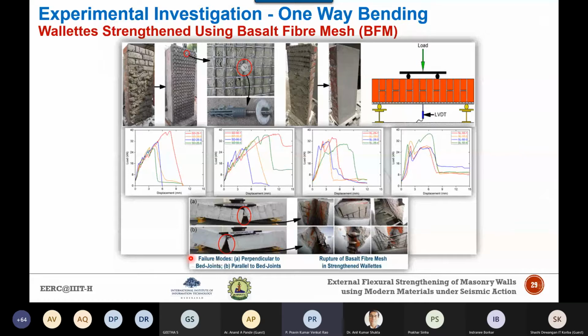Here also, especially for perpendicular to bed joint, your unreinforced masonry lies around 5 kilonewtons. Now the strength enhancement is up to 40 kilonewtons, you can see. Especially for the parallel to bed joints, the strength was around 12 kilonewtons for URM, whereas the strength has increased to almost 32 to 35 kilonewtons for the strengthened masonry.